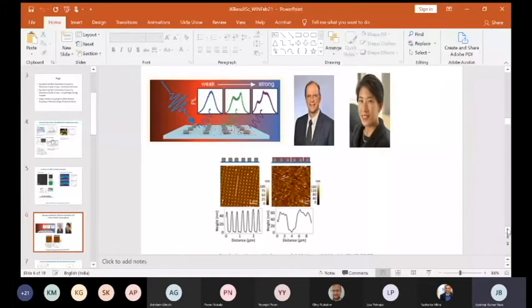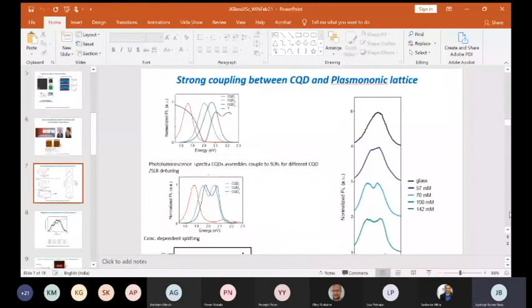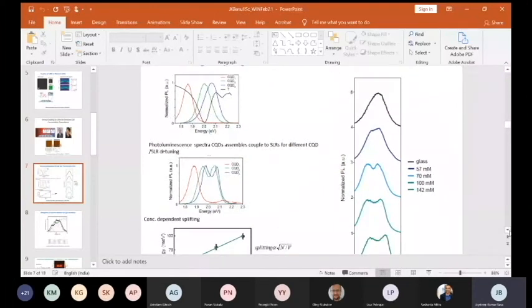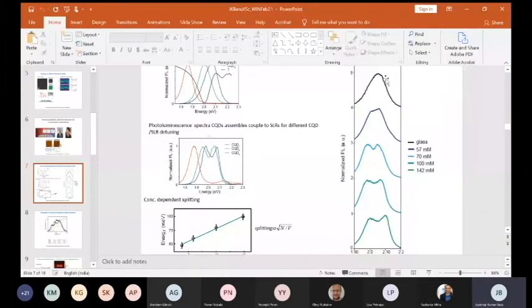Essentially, then what you are looking at is the emission, the photoluminescence from these quantum dots, the quantum dot layer, as they are on this template as shown in this schematic here. Now if you're looking at photoluminescence, initially when you just have this quantum dot layer, it gives a typical broad peak, as one would anticipate for this particular type of quantum dots. Then you start looking at the different concentrations of the quantum dots on these templates. As you start increasing the concentration of the quantum dot layer on one of these lattice templates, you start seeing a strong splitting that emerges.